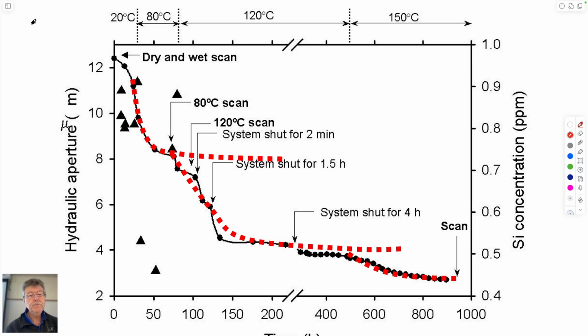So what you could do is, if you have Darcy's law, I guess this would be an area. If you apply a pressure gradient from end to end over a given length, you measure the flow rate, you can calculate permeability. If you know permeability, you can calculate equivalent aperture, which is what's shown here. And so this is a proxy for permeability. You could just as easily have plotted permeability, I guess. So it starts off at a quite tight, 12 micron fracture, very tight.